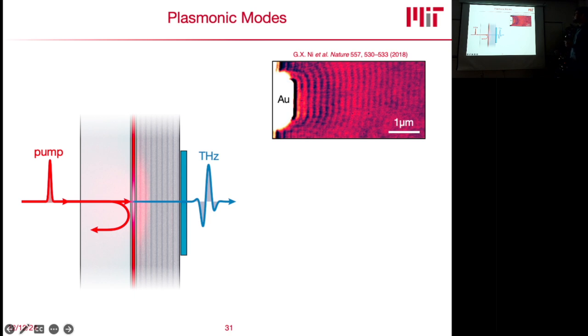And so this is now where we want to start looking at these plasmonic modes. People have had other techniques to measure those with scanning tips and strip lines, where they found that if you launch these plasmonic modes, in this case in graphene, they evolve on micrometer length scales. However, our spot size here is about 10 micrometers.